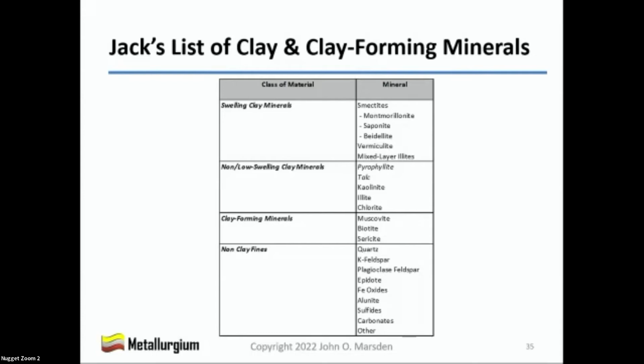There's a method called cation exchange capacity, which will give you an accurate quantitative measurement of swelling clay and non-swelling clay minerals present. When you combine this with XRD measurements, you get a pretty good estimate of the clay and fines forming minerals. Geez, that sounds pretty complicated and expensive, retorted Jack.